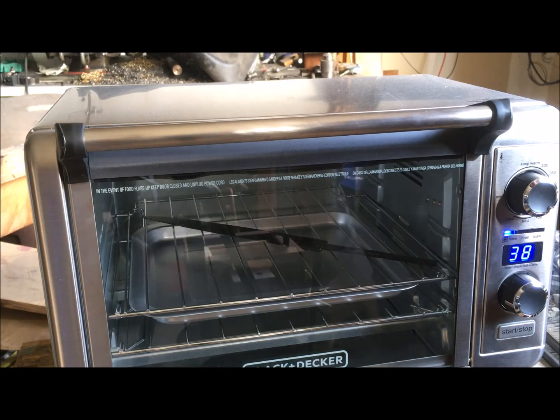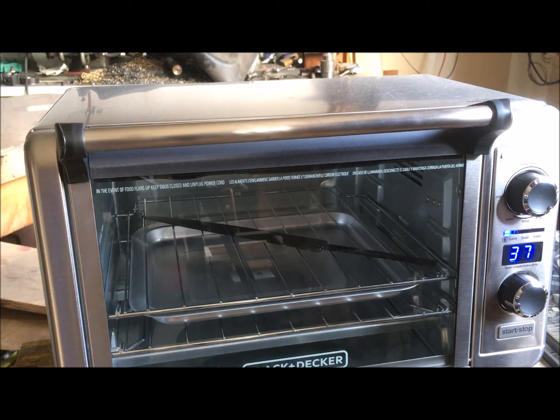So the blade quenched properly without warping on the edge or the back or anywhere. Yay, fireworks and trumpet fanfare. Before it even reached room temperature, I popped it into the preheated 425 degree toaster oven. And it's going to spend about an hour in there, just getting a preliminary temper. Once it's done that, I'm going to put it in the now cooled down kiln, which is also set at 425, and give it another longer temper, maybe a couple of hours. So I think the most tricky part of this is over for the moment. Now it's another temper and a bunch of sanding and grinding.